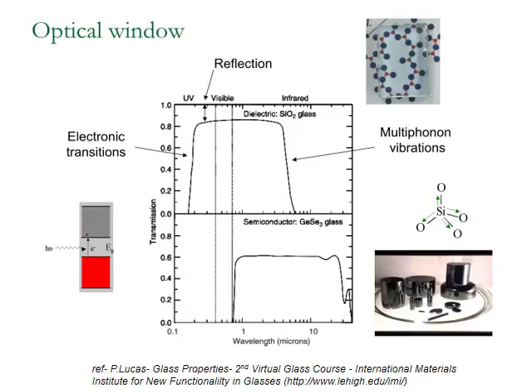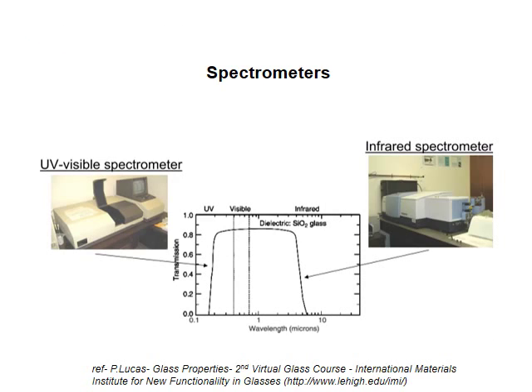The transmission window for different glasses will therefore be determined by the chemical nature of the glass. In this figure, you have the transmission window for silica and germanium selenide glasses. You see that germanium selenide glass is transparent above 10 microns, suggesting applications in infrared devices, such as night vision devices. The transmission window spectrum is in fact a composition of spectra obtained in two different equipments.